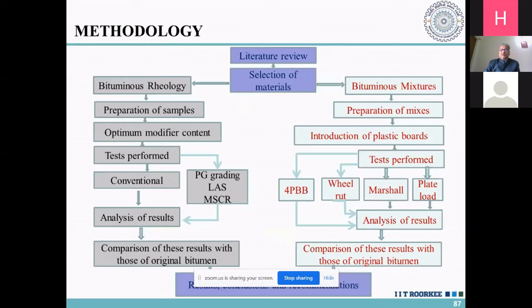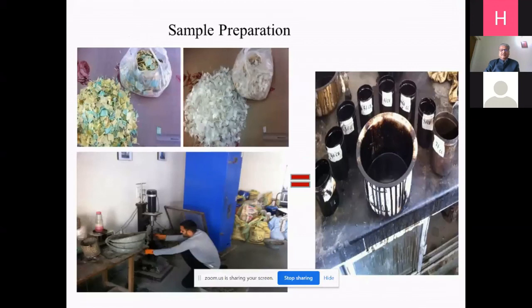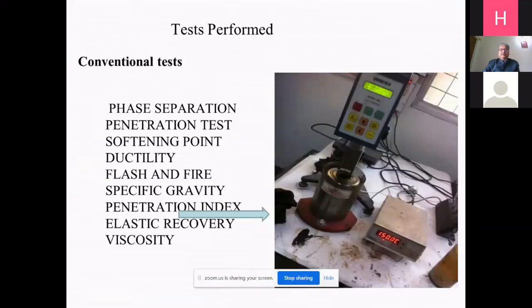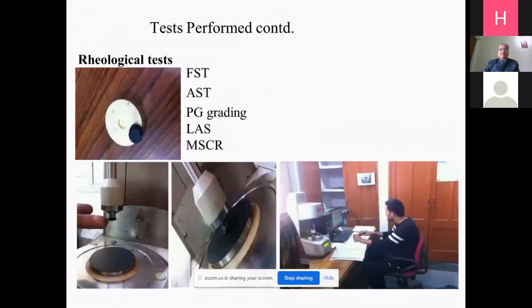This work I am showing you by Ravind Singh. He did this work here as an MTech student. He used these two types of plastic materials. You can see here, this is the cement carry bag, this is a normal carry bag. He mixed these materials in the bitumen, and different types of results were achieved. These are the conventional tests which we did: phase separation, penetration test, softening point, ductility, flash and fire, specific gravity, penetration index, etc. And these are the rheological tests.